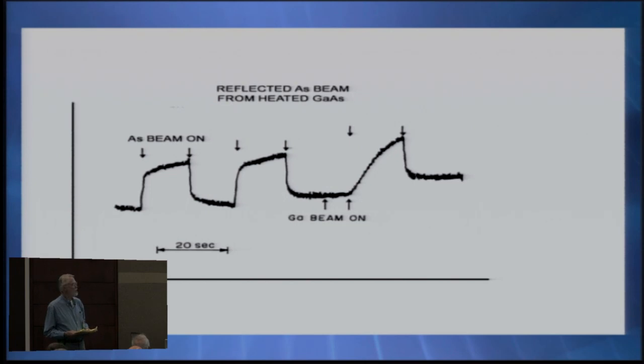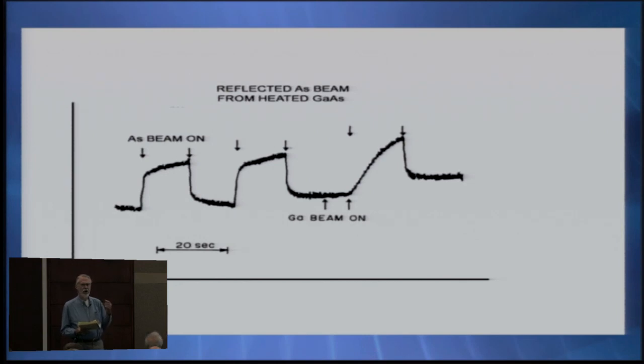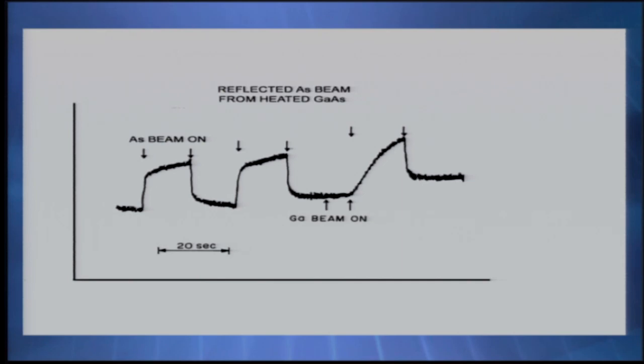But when there was a little bit of gallium on the surface, it behaved totally differently. And you can see that there is an uptake of arsenic. It's not bouncing off the surface when there's gallium present. So this suggested that here is a way to make stoichiometric compound films. People had done a lot of work trying to evaporate compound semiconductors prior to this. They would do such things as putting a gallium arsenide source in a tube and heating it up and then figuring out that somewhere along the length of this tube, the atoms would be arriving at the surface to make a stoichiometric film. Well, what this showed was that you didn't need to worry about that. You could make a stoichiometric film just from these molecular beams. And this was a pretty convenient way to do it.